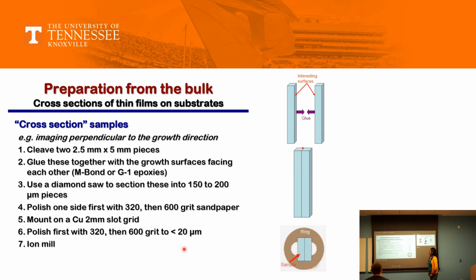For example, this was your irradiated face here. You glue the irradiated face, or the face that interests you. You take 2 samples and you want to analyze this part because you created damage from here to here. You glue them with any super glue. So you will have a configuration with 2 interesting zones, which cross this joint in both directions. There is where most of your information lies, where your voids, bubbles, and dislocations lie.